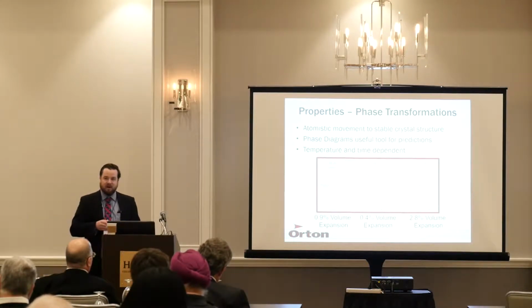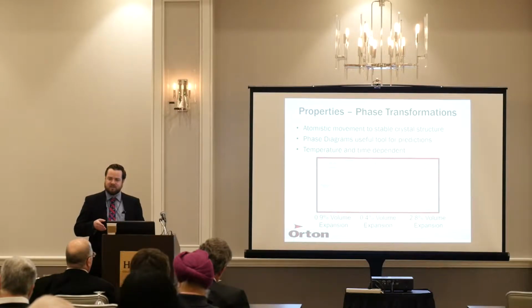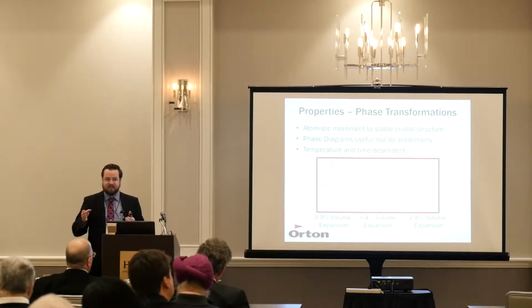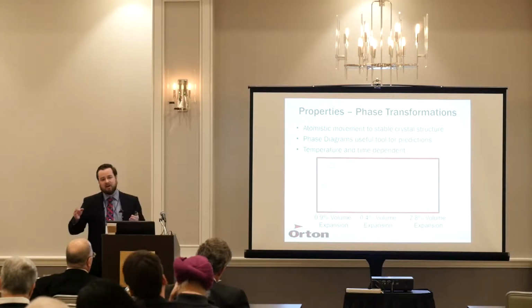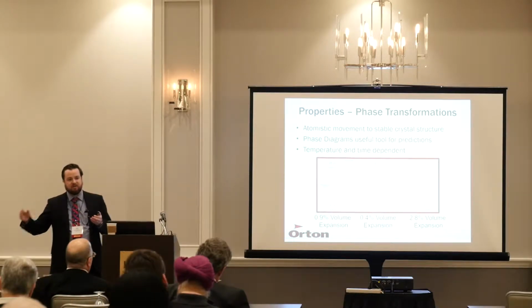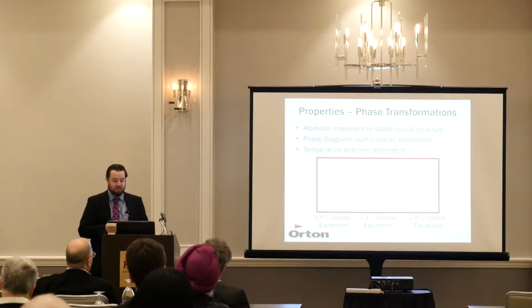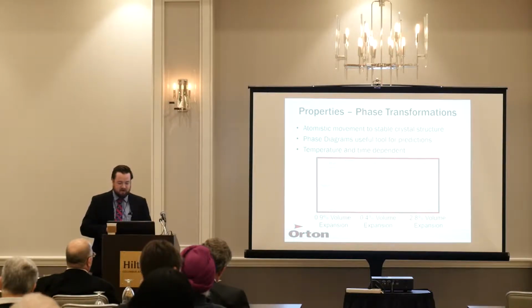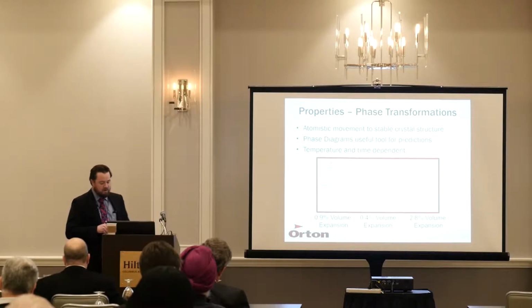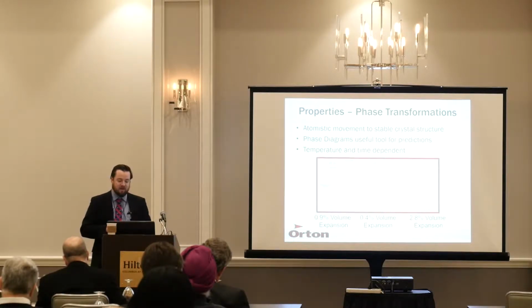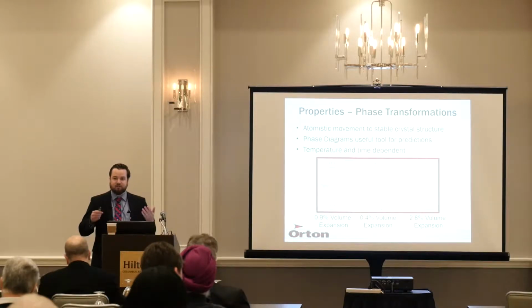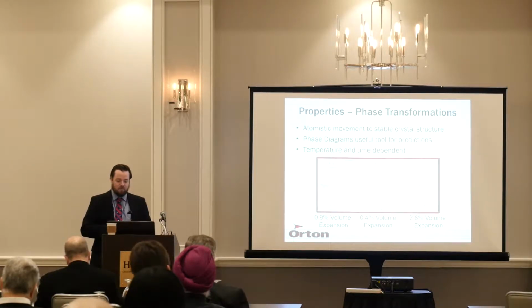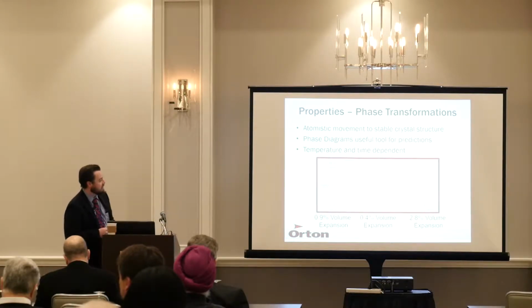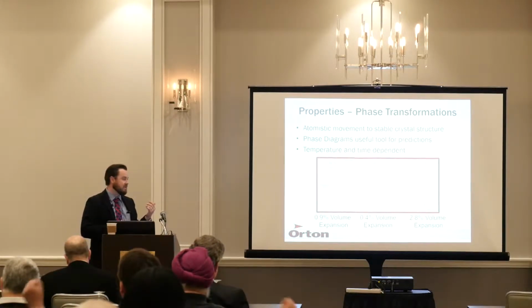So that's always something to keep in the back of your mind, especially if you're a glass processing facility. I imagine if you have a refractory brick or a ladle, over time, it might not be seeing the high temperature that is the max use, but it's going to provide enough energy input to eventually reach a stable phase if it wants to. These are different types of phase transformations that can occur. I've listed at the bottom here a couple of the different volume expansion contraction measurements. So how do we know if it's high quartz or low quartz? Well, we have the temperature there. This occurs around 573 degrees Celsius, and it's correlated to about 0.9% volume expansion.